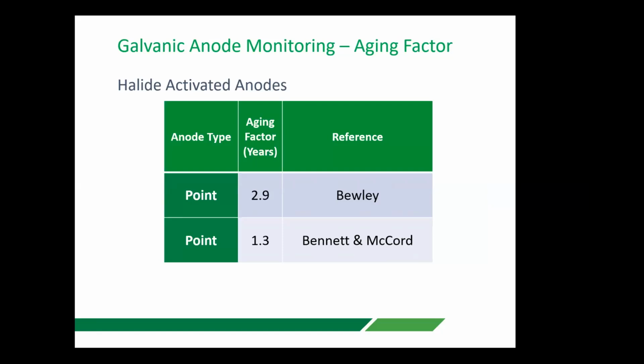Now, when I looked around in the literature to see how other anodes, remember these are alkali activated anodes, there are halide activated anodes, chloride, bromide, and such. I could only find 2 examples of results that were published, and I determined the equivalent aging factor of those. I couldn't find anything beyond 3 years, so there's a clear difference between alkali activated anodes, which allow the corrosion products to migrate, and the chloride or halide activated anodes. Again, they use zinc, but what happens is zinc corrosion products are not soluble because the pH is quite low, and that tends to accumulate very quickly around the zinc mortar interface. That subsequently reduces the current flow.